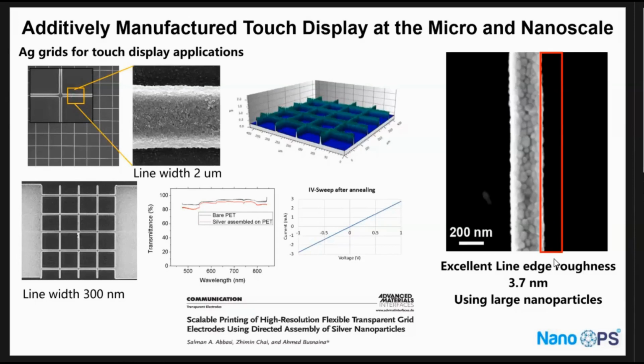So that's pretty good. And then they asked, how can you print nanoscale so that it would be smaller than the wavelength of visible light, so that you don't see the screen door effect, for example, when you look at that. And so we did that, and we made a line width of about 300 nanometers. You can see here, close up, the line edge roughness is pretty good for that application as well.